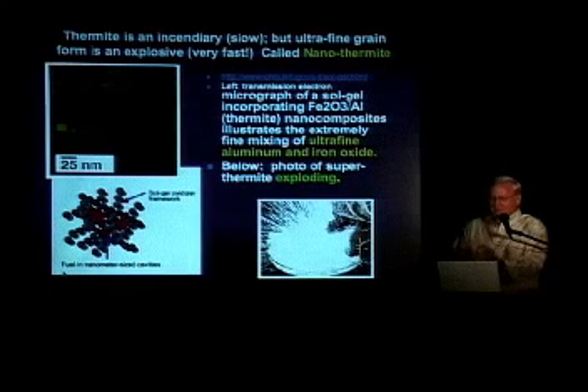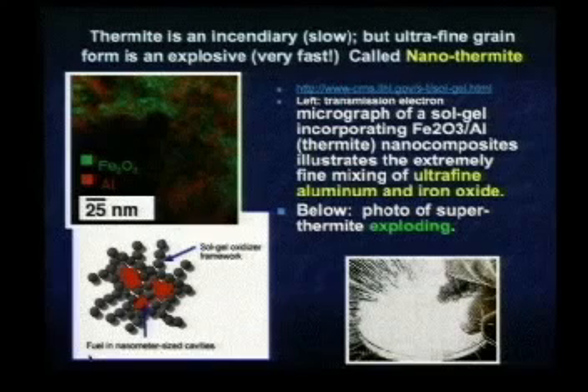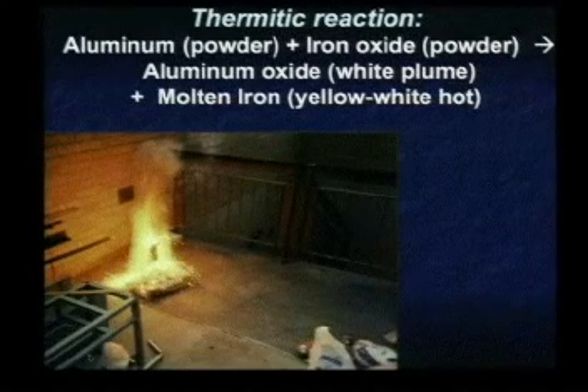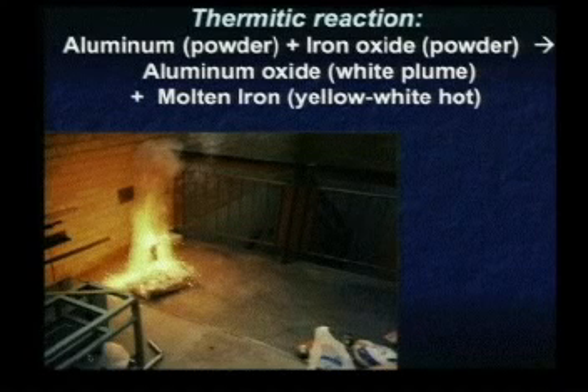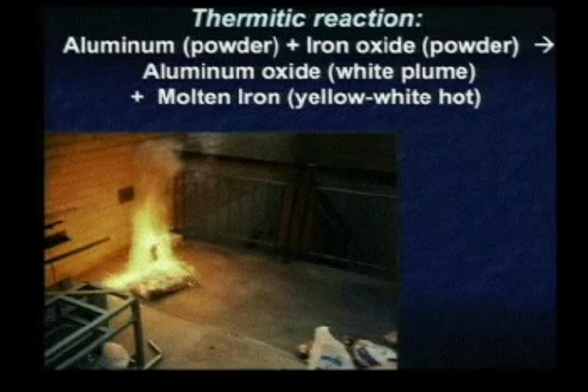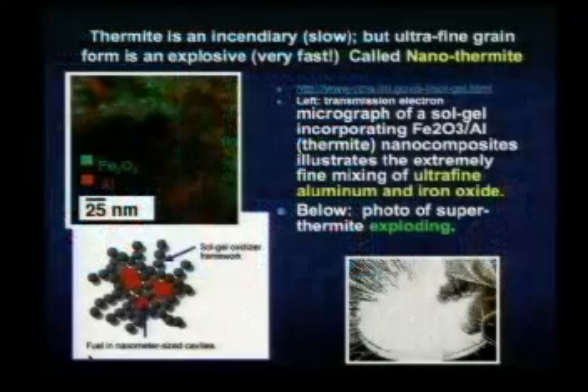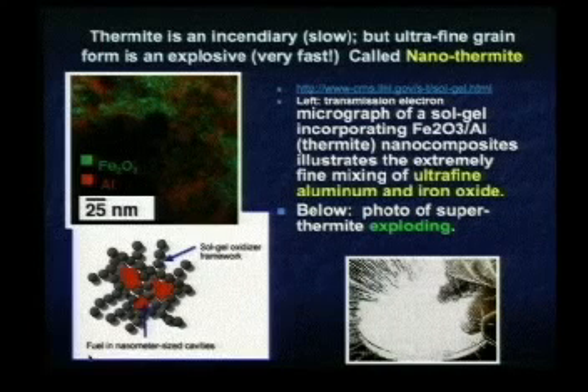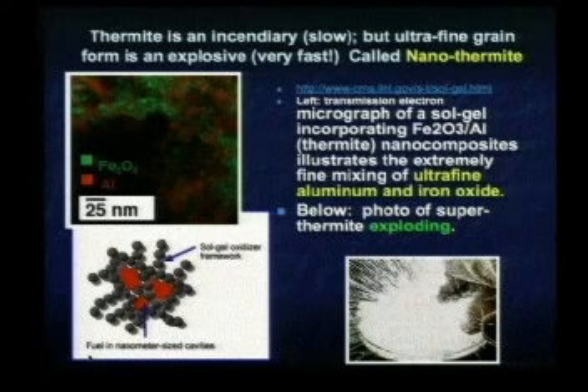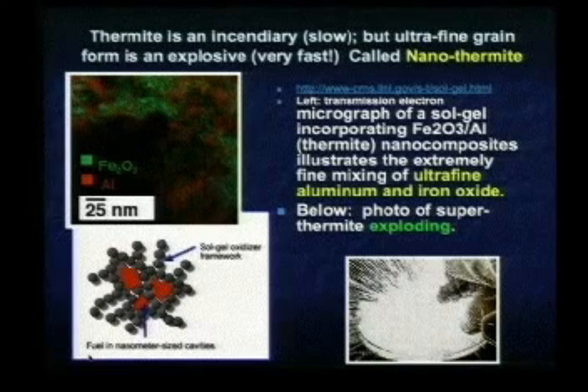One thing I'd like to get perfectly clear, if I can possibly, and I wish there was someone here from NIST who would listen to this. Thermite, I agree, is an incendiary, ordinary thermite, which means powders of aluminum and iron oxide mixed together, and they burn as incendiary. So you see this molten material. This is ordinary thermite here in the photo, and you see the molten iron coming out of that. It's an incendiary. It melts things. But the ultrafine grain form is an explosive. It reacts very fast. The smaller the grains, the faster the reaction. That's been demonstrated in published papers.